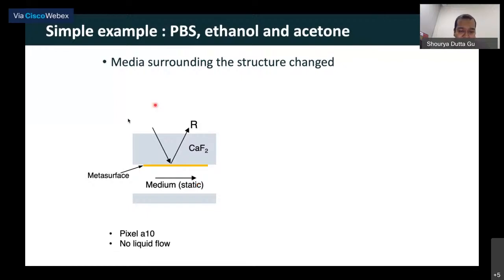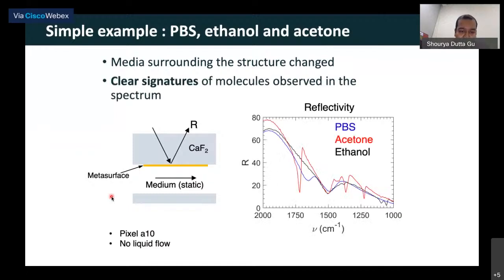The system that we use is basically a microfluidic channel where we have the metasurface encapsulated in this channel, so that we are able to flow liquids and also measure in static condition. Now, if I take three different cases, when this chamber is filled with either PBS or acetone or ethanol, if you look at the IR spectrum, the reflectivity versus wave number, we see three different spectra, and each of these bands, the sharp features that we see in the red, the blue and the black one, can be identified with the vibrations in these molecules that we are looking at, right?